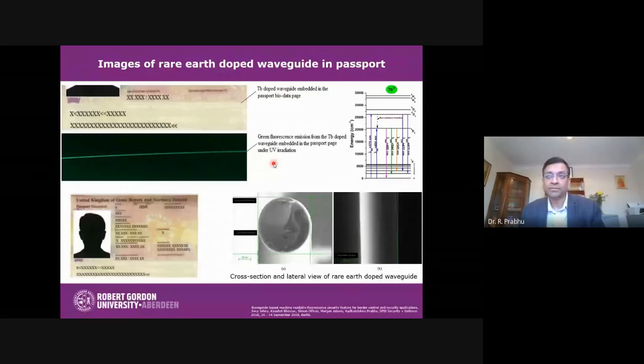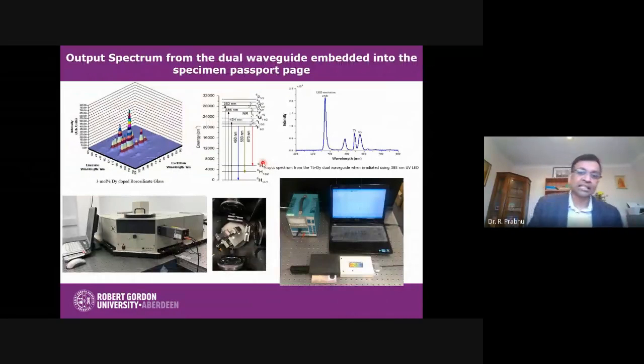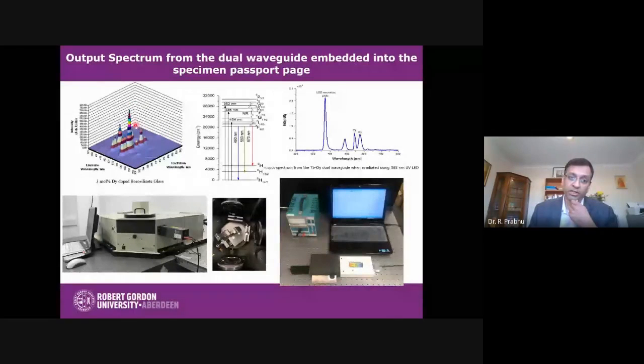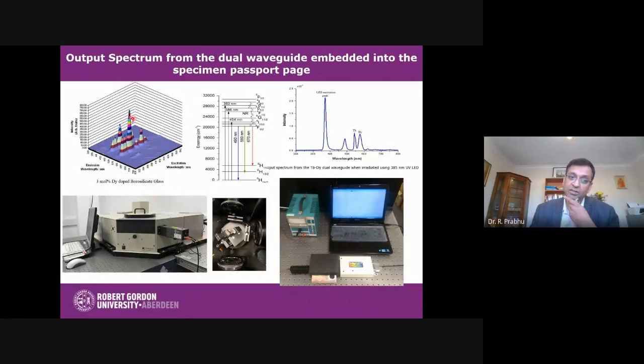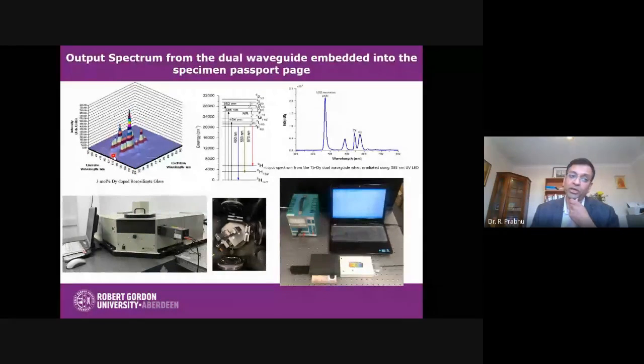And this can be an additional security feature in addition to other security features like RFID or biodata. Now, can we enhance the security by adding spectral barcodes? So we use another rare earth element called dysprosium, which has different emission. We characterized using Edinburgh spectrometers, and this is the excitation and emission pattern from dysprosium doped into the glass fiber. And we integrated these two, terbium as well as dysprosium, as two fibers very close to each other. Then we got a security pattern which is represented here.